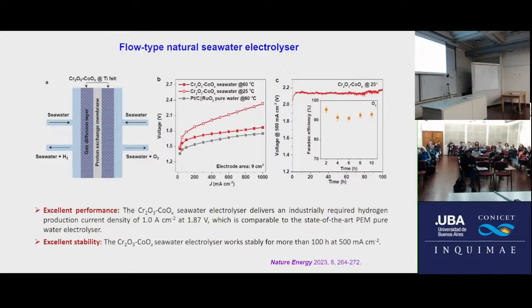Okay, we use a device to demonstrate all the material performance. This green line is the commercial catalyst. This commercial catalyst is very expensive, right? It uses noble metal and pure water. Okay, this red square line is our catalyst in seawater. Okay, this performance is close to the green line already, right? We also study stability. So 100 hours, no problem. For other people, they only ran several hours.